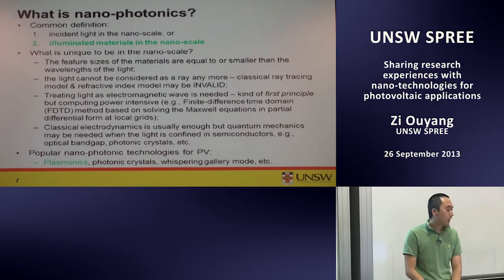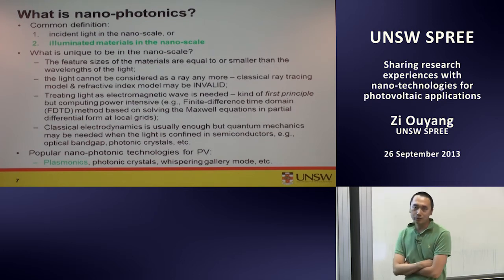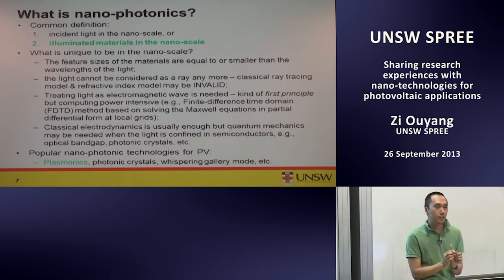So you have to consider light as an electromagnetic wave. One of the popular methods used is the finite difference time domain method, called the FDTD method, to solve the Maxwell equations in partial differential form at local grids. So you really look at what's happening exactly at the nanoscale, and you just add more and more, let it repeat, and you can see what's happening at a larger scale. So that's one typical method of investigation.